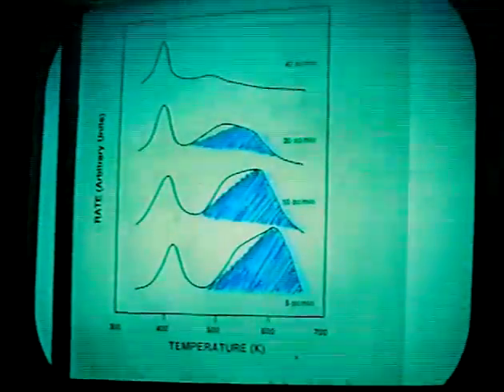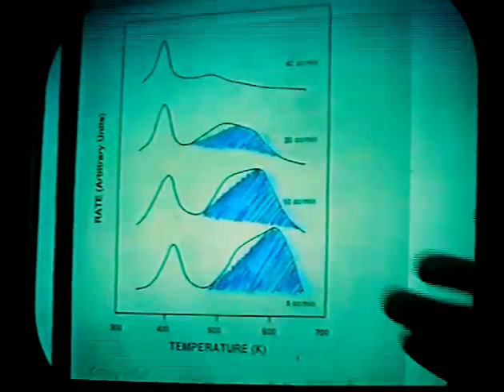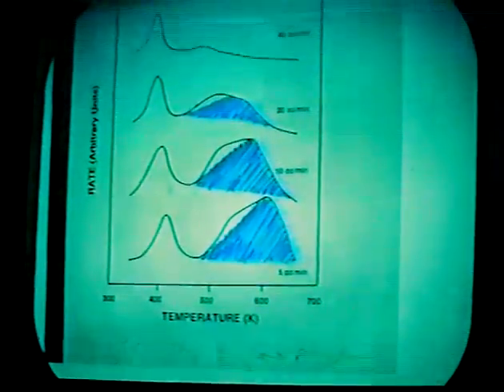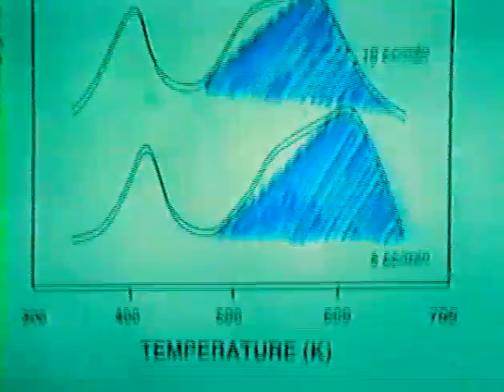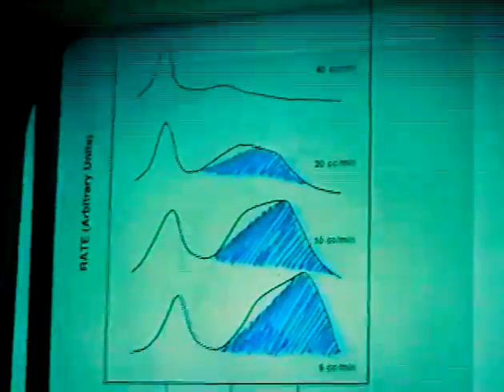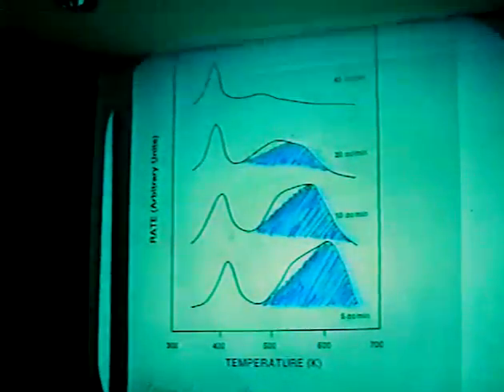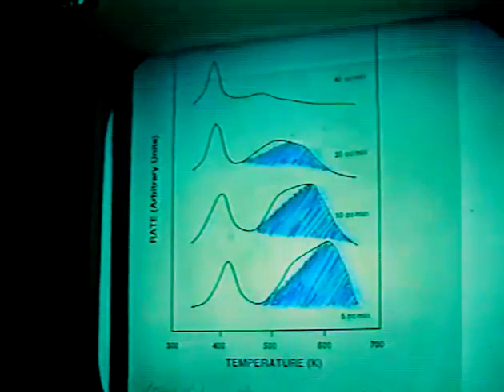You'll notice that as we increase the flow rate, and these are carried out in the traditional, conventional way that you would do temperature programmed desorption, we adsorb hydrogen and then heat the sample up and look at how hydrogen desorbs. You'll notice that the character of the spectrum changes as we increase either the flow rate or the heating rate. This is indicative of the presence of a subsurface site, and for those of you who are interested, there is literature in this area by Leary et al.